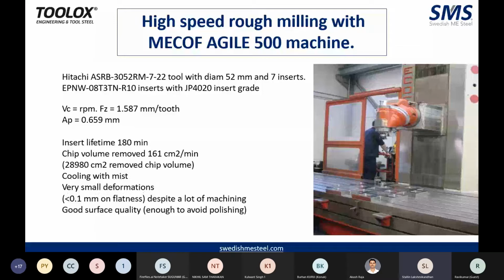So high-speed rough milling has been done. As per the example that we have given here, the insert lifetime has run around 180 minutes, and the volume of chip removed is 161 cubic centimeters per minute. Even though you have removed close to 30,000 cubic centimeters of chips, the deformation is very, very minimal. It is able to maintain less than 0.1 mm of flatness, even though you have done extensive machining with this.